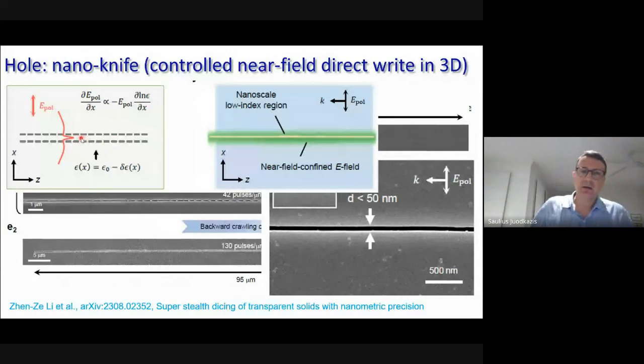Those regions with the lower refractive index are attracting, because of that interface between glass and a little bit reduced refractive index of the glass along propagation, light will be concentrated. Certainly, in this case, there is no very clear interface, but obviously the physics is the same. Light is trying to be in the lower refractive index part if there is a very sharp gradient of refractive index. So this is the reason why we can concentrate light.